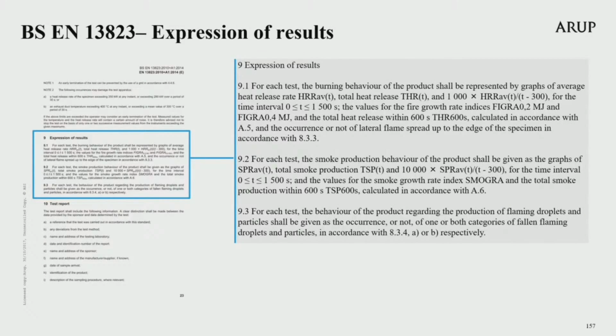Section 9 of the standard sets out how the results of this test must be expressed. There is a lot of data and analysis required, and it is essential to read the BS EN in full to understand this. These are key to the European classes. In short, the burning behaviour is represented by a series of graphs showing the average heat release rate, the total heat release rate, and the fire growth rate indices versus time. The smoke production behaviour is given as a further series of graphs of the average smoke production, the total smoke production, and the smoke growth rate index. Later in the classification standard, the designation s will appear, and it is calculated here. The production of flaming droplets and particles must be confirmed as an occurrence or not for the product. Later in the classification, the designation d will appear, and it is calculated here.